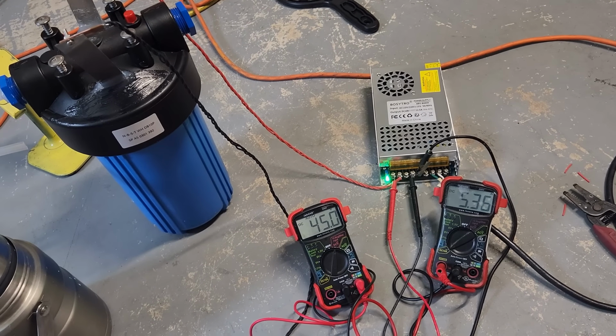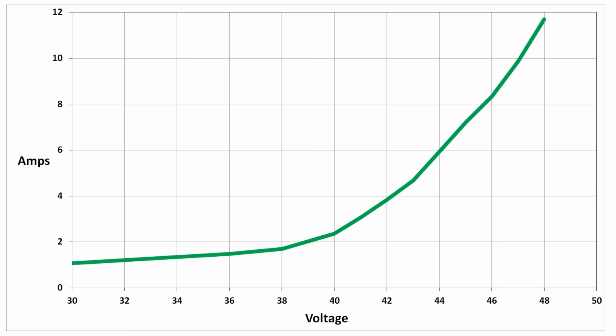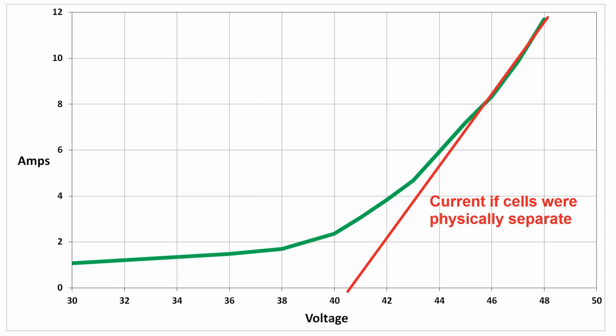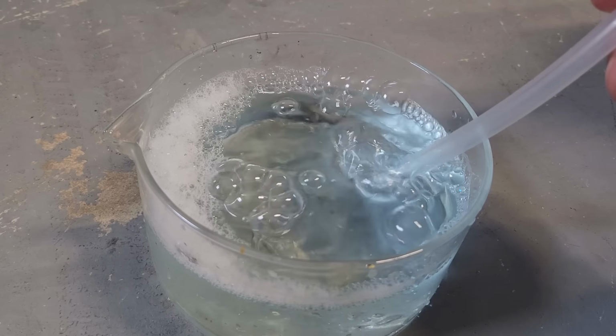Here's a graph of current versus voltage. If the cells were perfectly separated, we'd have zero current until we hit around 40 volts, which is about 2 volts per cell. But because of the bypass current I mentioned earlier, we get a little bit of current before all the cells start electrolysis. And there's some gas production.